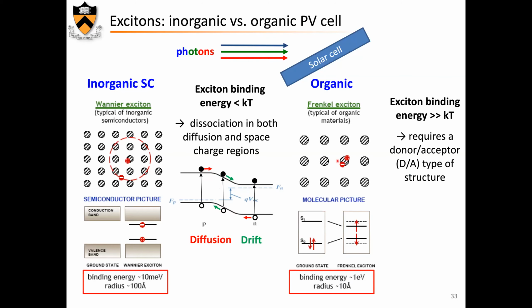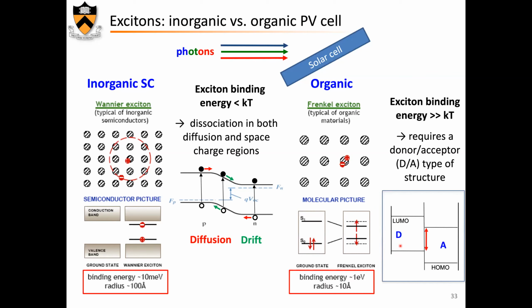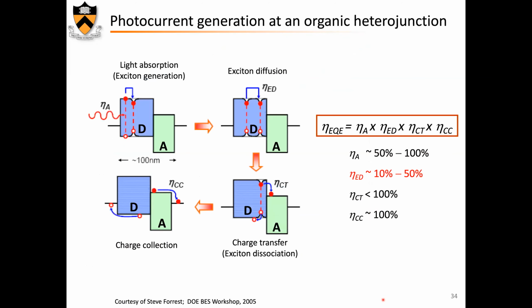In organic material, the situation is more complicated. As I said before, the exciton is a Frenkel exciton, a small radius exciton, with a large binding energy of an eV or so. So a field like this one cannot separate, dissociate the two. And it requires the use of two organic materials arranged like this one, where this one, which will be called the donor, has a HOMO level and LUMO level higher than the HOMO level and the LUMO level of the acceptor.